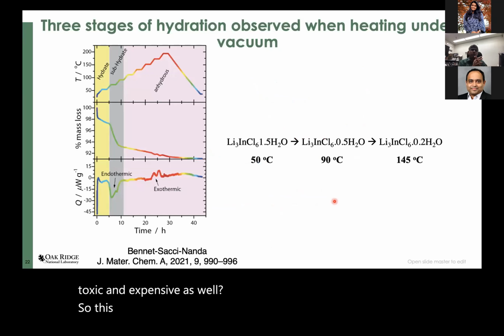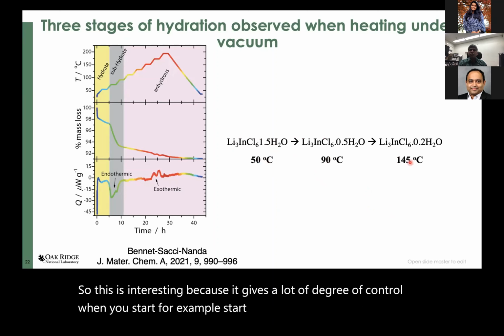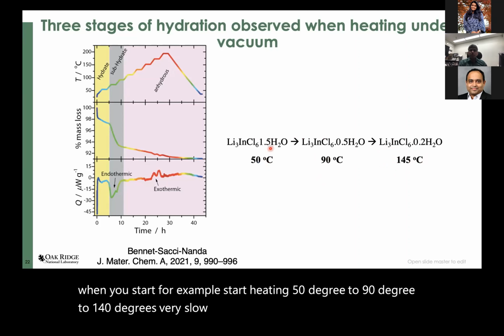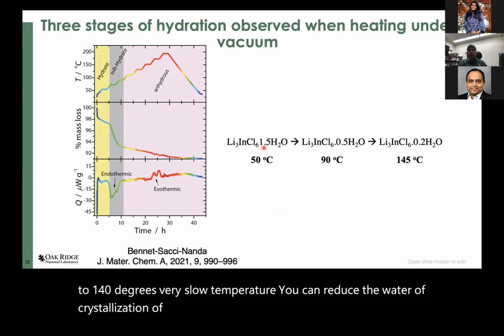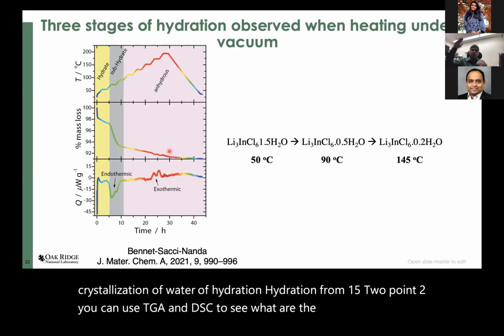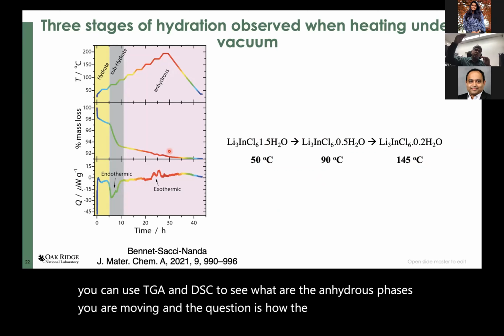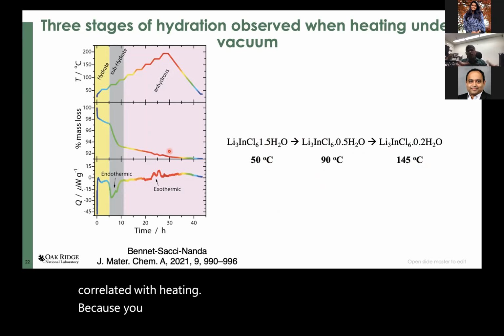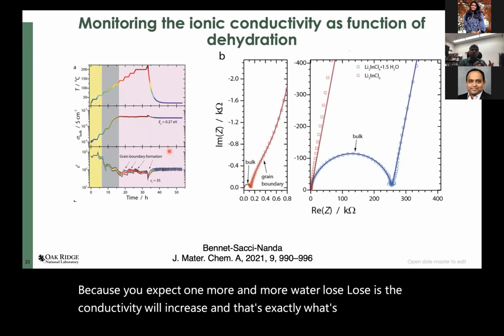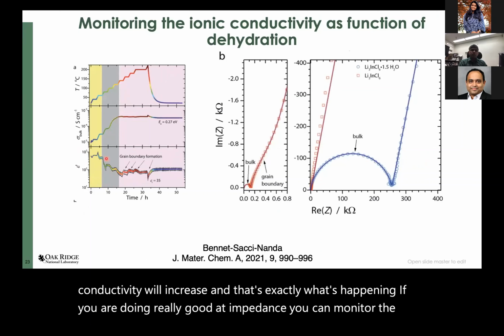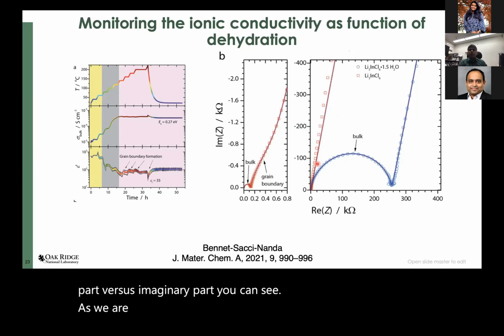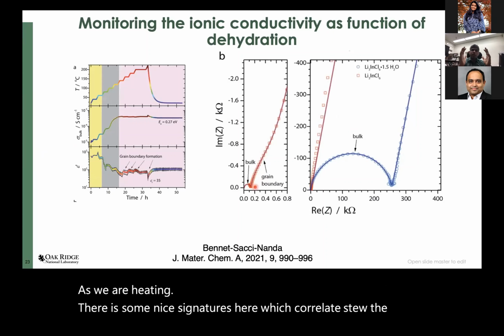So this is interesting because it gives a lot of degree of control when you start, for example, heating at 50 degrees to 90 degrees to 140 degrees, very low temperature. You can reduce the water of hydration from 1.5 to 0.2. You can use TGA and DSC to see what anhydrous phases you are moving through. And the question is how the conductivity correlates with heating, because you expect that when more and more water is lost, the conductivity will increase. And that's exactly what's happening. If you are doing really good impedance, you can monitor the real part versus imaginary part. You can see as we are heating, there are some nice signatures here which correlate to the impedance becoming lower and lower and lower.